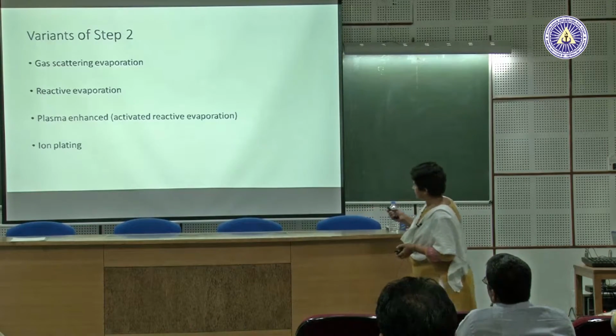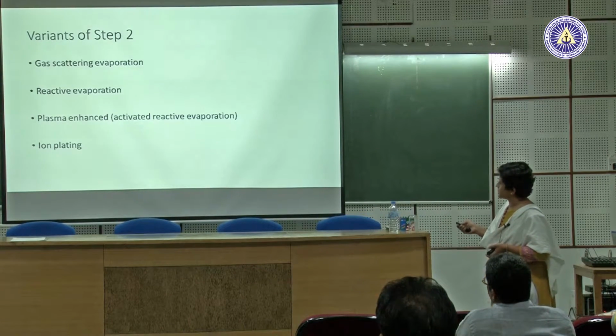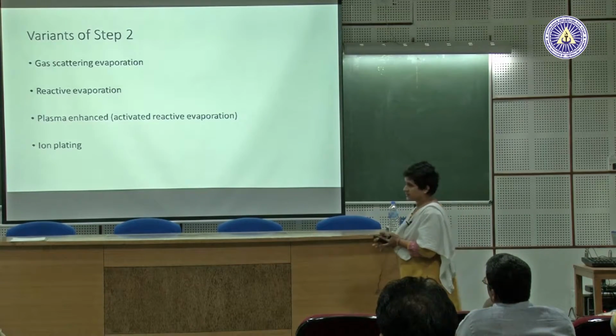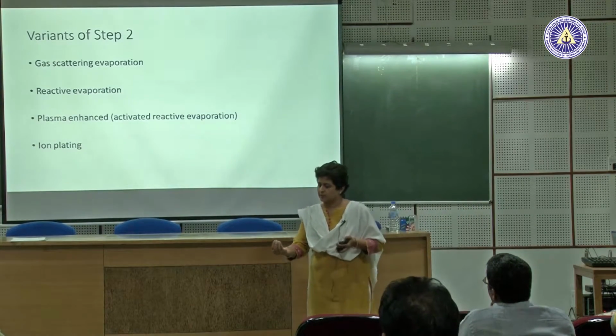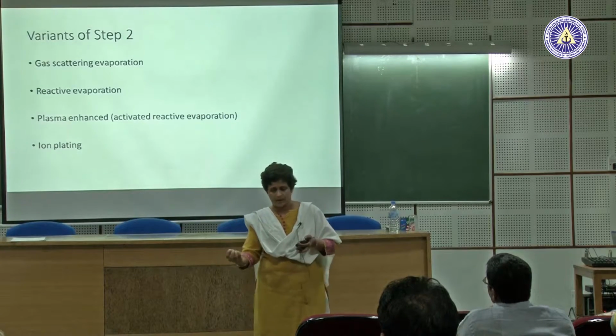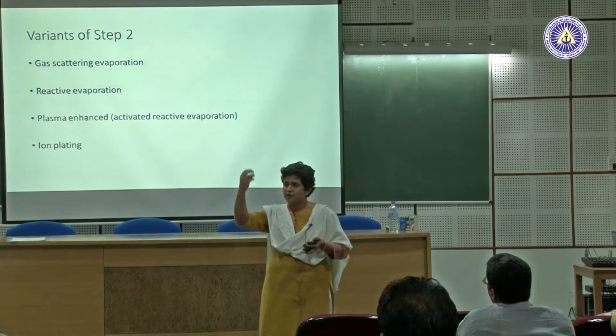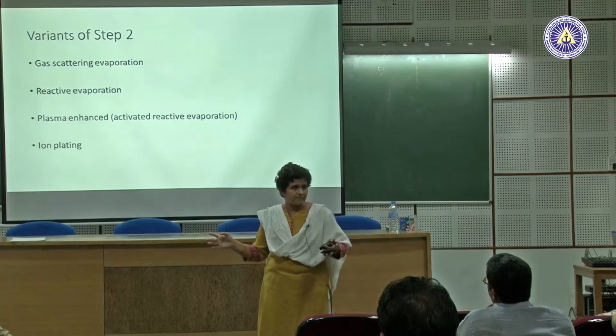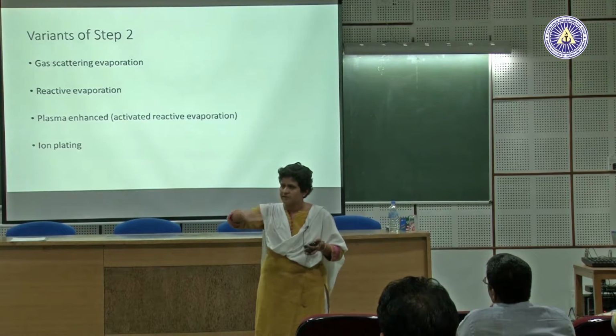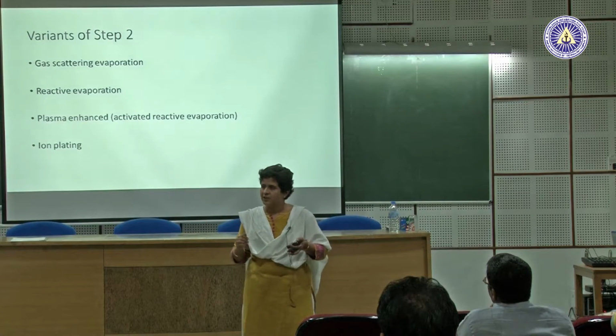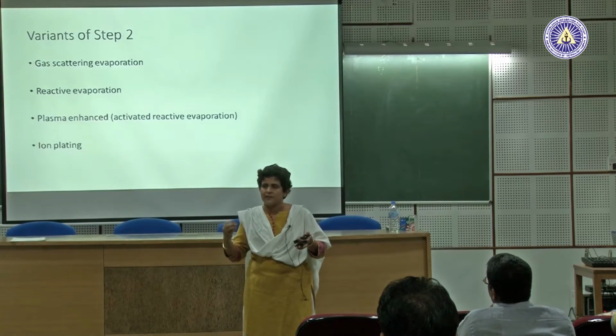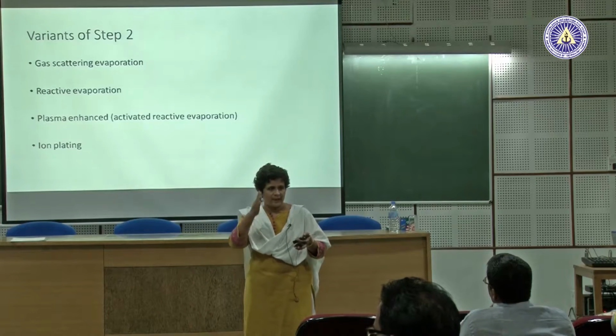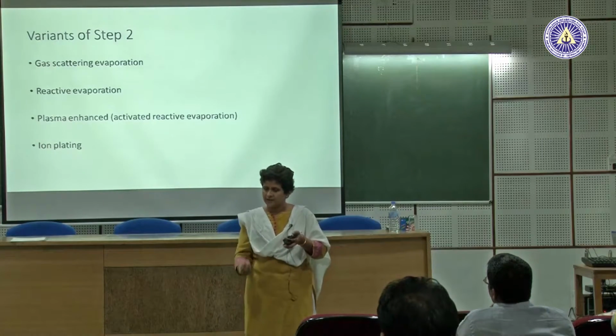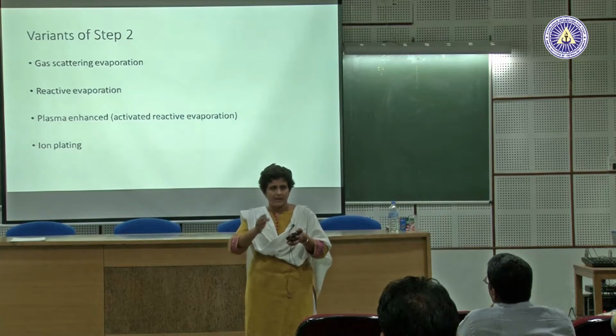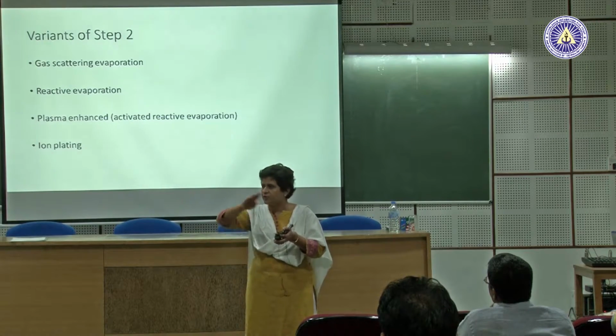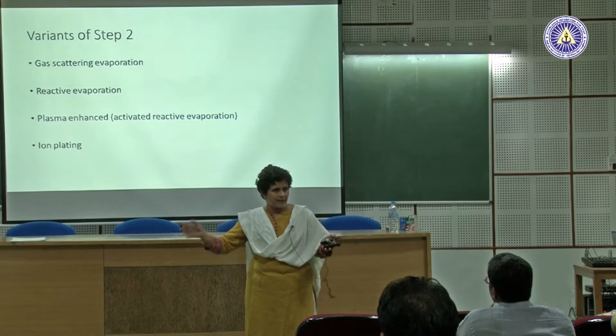These are variations of step 2, and the first one is gas scattering evaporation. So, I just told you that when the vapor phase, the atomic form, is created at a source, it should come to the substrate without getting reflected, right. And if I do that, I have a non-uniformity going from center to the edge. So, if I want to make it uniform, one way is also to provide scattering. Right now, deposition is line of sight, starting from the source and getting deposited on the substrate. But if I provide a lot of scattering, this angular distribution gets more random, and that provides uniformity.